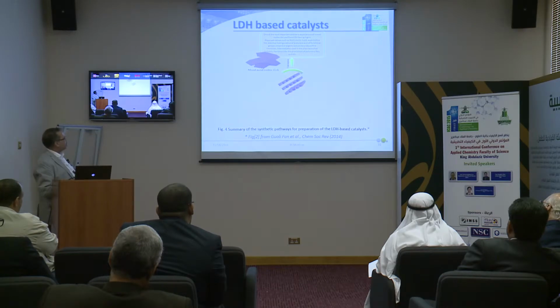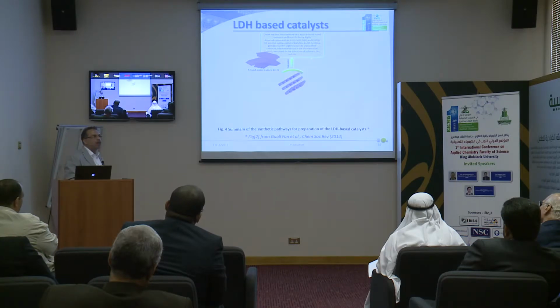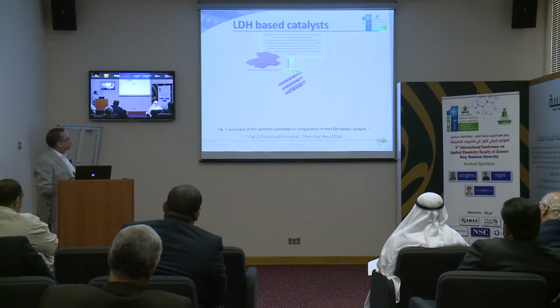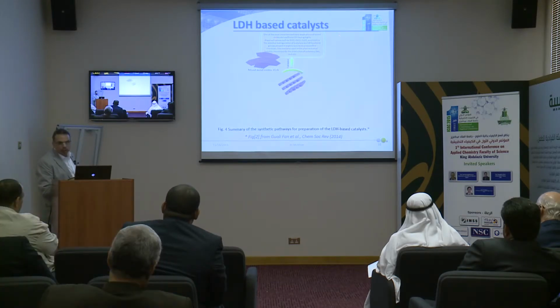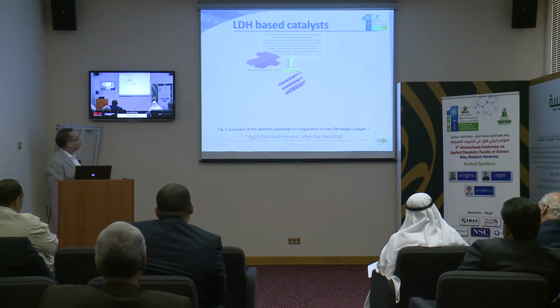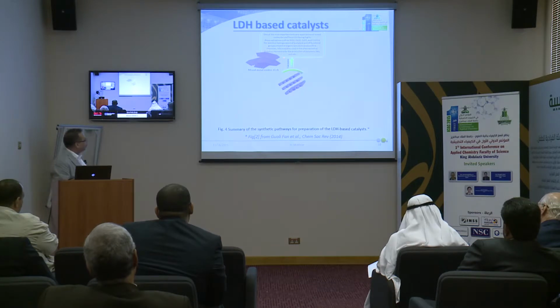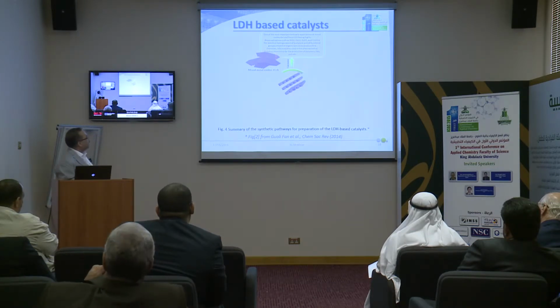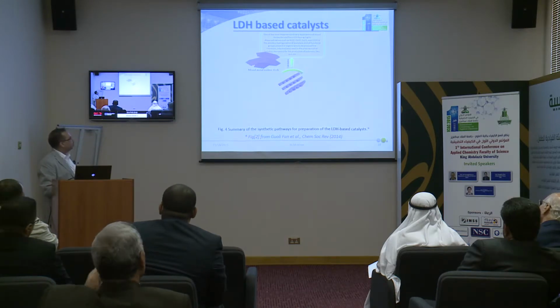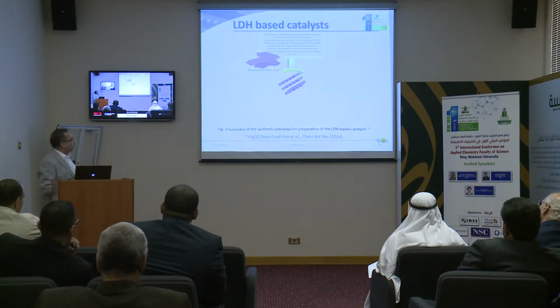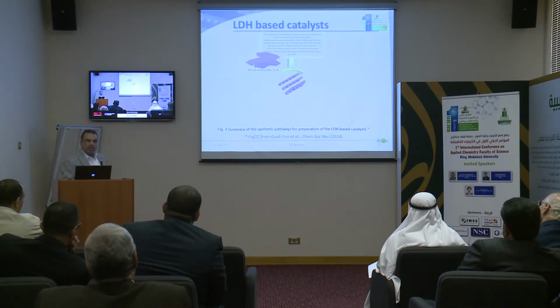For example, the layered double hydroxide, once it's collapsed into the metal oxide, we have usually prepared the metal oxide via the hydrotalcite route. What's the advantage of this material? Once you synthesize the material at the beginning in the form of layered double hydroxide carbonate, then you calcine this material to have the metal oxide. You have a unique property for the metal oxide you prepared now, because you're introducing more Lewis acid and more Lewis base sites, and it finds many applications, especially if you substitute the aluminum by nickel or cobalt or copper, whatever. So you can prepare different metal oxides via this route.